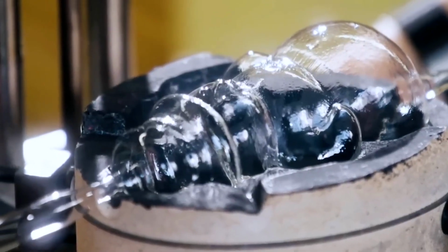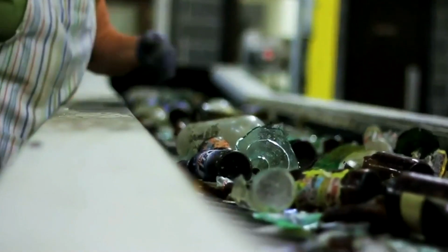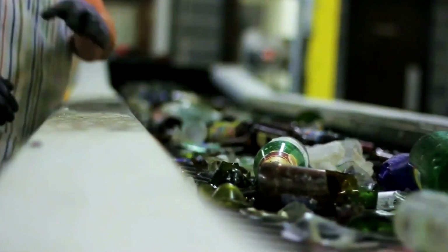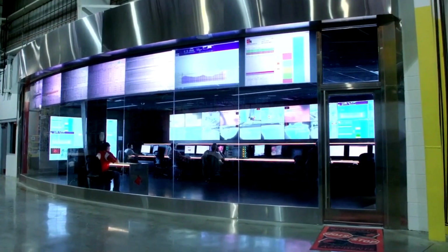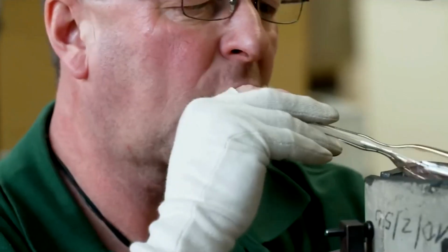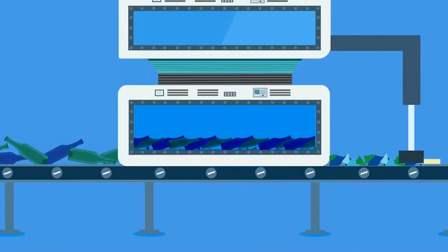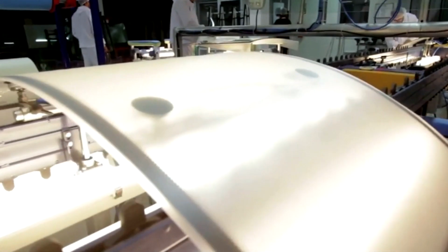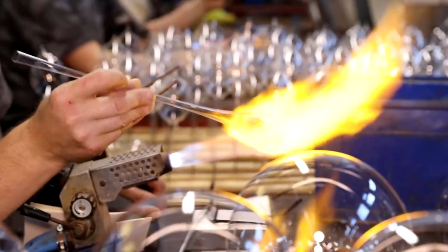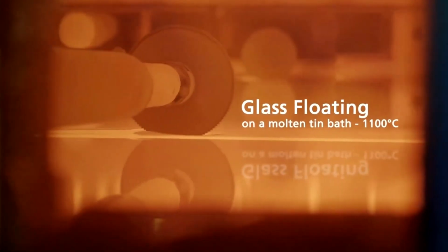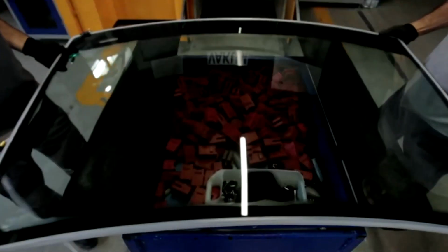To create new glass, the cullet is mixed with silica sand, soda ash, and limestone. The addition of 20 to 70% cullet allows the mixture to melt at lower temperatures, reducing energy consumption by up to 40%. The mixture is heated in a furnace until it becomes a homogeneous liquid. For automotive glass, the molten material flows onto a bath of molten tin in the float glass process. The glass floats on the tin, spreading naturally into a continuous ribbon with a perfectly flat surface. The temperature here is held between 1,800 and 2,000 degrees Fahrenheit. Edge-forming rollers control the width and thickness as the ribbon moves forward.